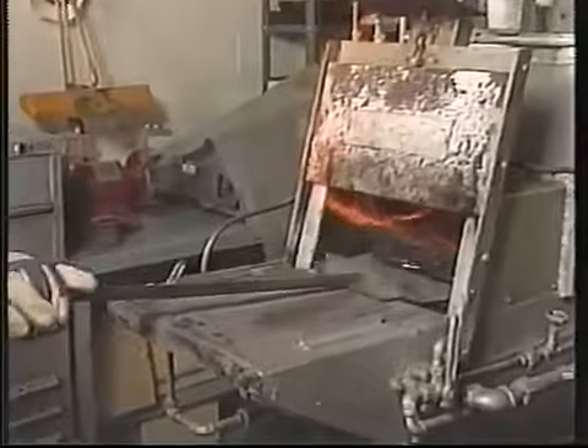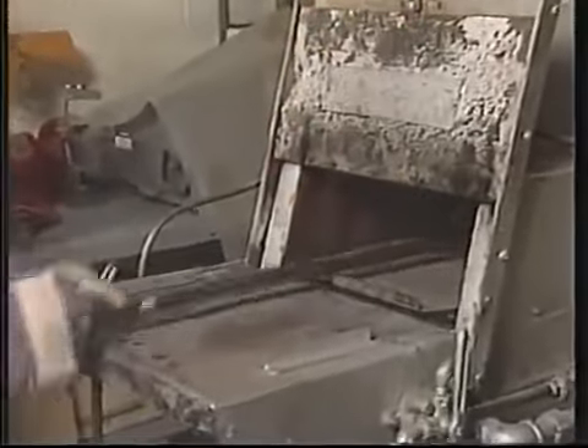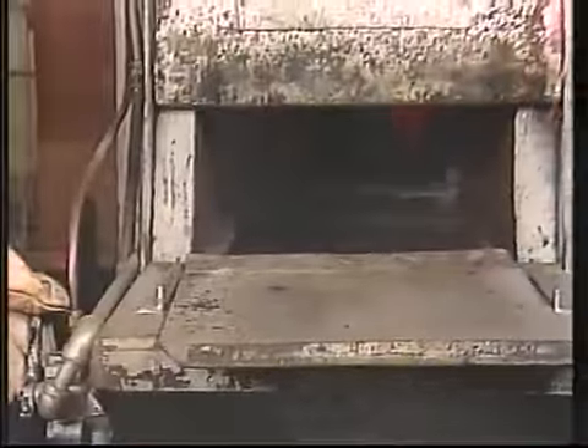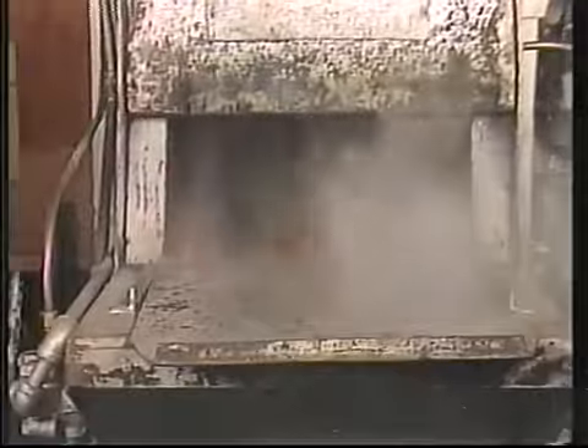The operator loads the blanks into an annealing basket, then puts them in the annealing oven. The annealing operation is intended to soften the piece. The oven is running at approximately 1200 to 1250 degrees. After the pieces are finished, they're pushed into water. This is a quick cooling action which completes the annealing.